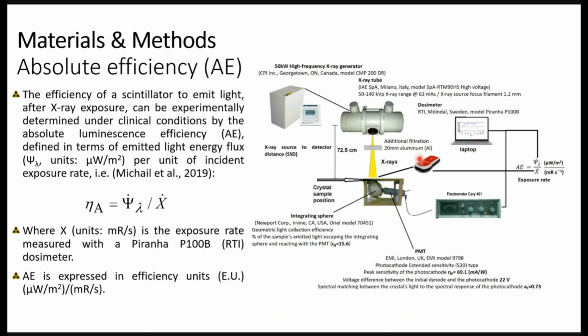Also, we measure the incident radiation on the surface of the crystal by placing a calibrated digital dosimeter, as we can see here. And we have also this reading. So by dividing the light energy flux with the X-ray radiation, we conclude to the absolute luminescence efficiency, which describes the performance of every scintillator, and with this measure we can compare their relative performance. The units can be seen here, and they are expressed in efficiency units.